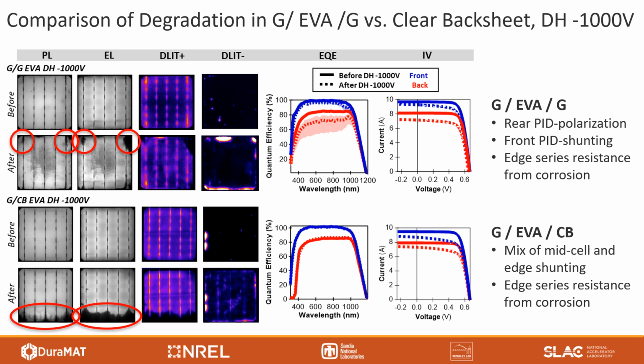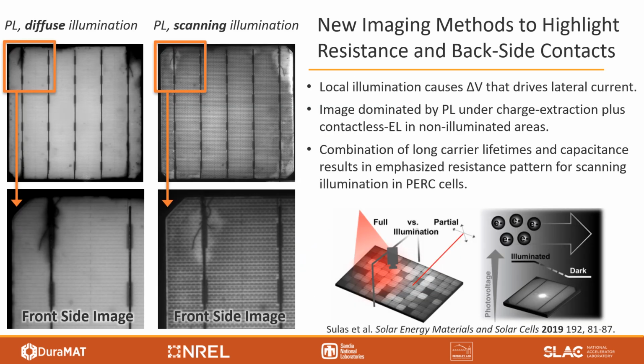In both cases, the series resistance manifests as areas being exceptionally bright in the PL while they remain very dark in the EL. Here's a zoomed-in view of PL images showing that series resistance effect that I'm talking about, and I'll just quickly mention a different method for really visualizing series resistance in these PERC cells. There are multiple ways to measure photoluminescence, including using either a full area diffuse illumination or illuminating with a scanning laser beam. For PERC cells in particular, we see the series resistance effects become really emphasized with the scanning laser method. And we also find that we can use the scanning laser method to visualize the backside PERC local contact pattern even when we're imaging from the front side of the cell.